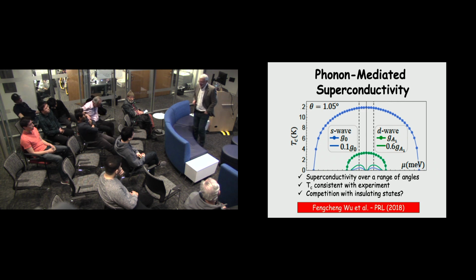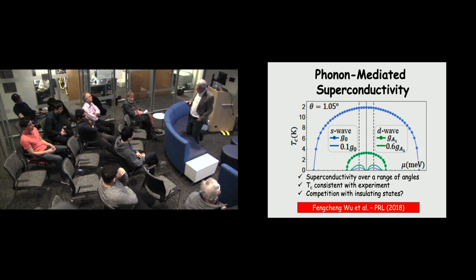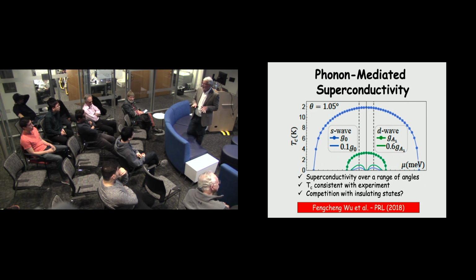I don't think so. I mean, this magic angle phenomenon, by which I mean that the flat bands emerge at a finite twist angle, and the width of the band is a non-monotonic function of twist angle, I think that's a function of having more than one Dirac cone. But people have studied a similar effect, interaction-induced superconductivity, in systems with two graphene layers that are on HBN that's nearly aligned. So the HBN plays a role in that system.